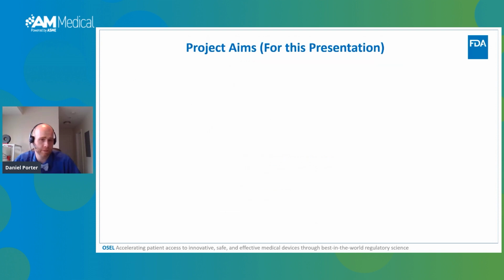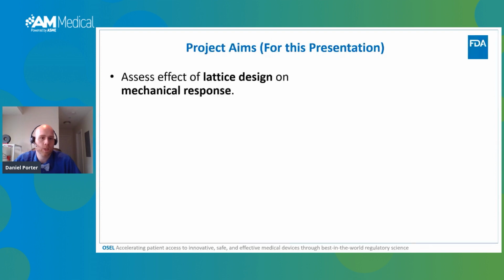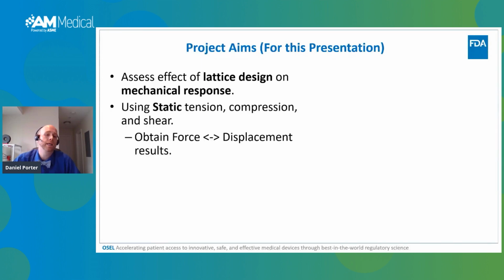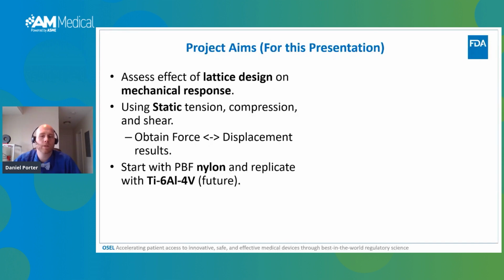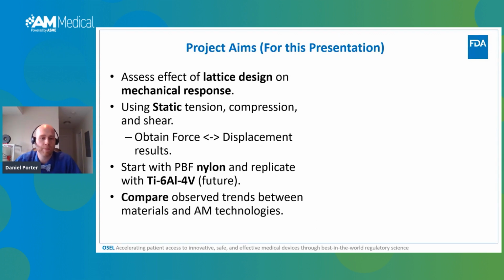More specifically for this project, we want to assess the effect of lattice design on mechanical response for some lattice coupons. We're going to do that by testing static tension, compression, and shear. And the outputs are going to be force and displacement. We're going to start with an AM system we have in-house, which can do nylon. And then we're going to, in the future, fabricate these samples in titanium alloy, and then back out and compare trends to see if what we found in nylon holds true for the titanium, or if things changed a little bit.